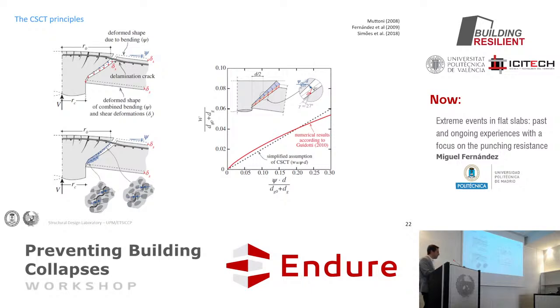And in fact, if you calculate them, you see that it is not linear as I was doing with my hands, but both kinematical parameters are related, namely for slender slabs. For compact footings and so on, it's not the case, then you need the two parameters. But for slender flat slabs, this is the case. So you can assume linearity between both parameters, psi and delta. And this allows you to calculate that the key parameter, which is the opening of the crack, this w, which is over here, is dependent eventually only on one parameter, which is, for instance, the rotation of the slab.